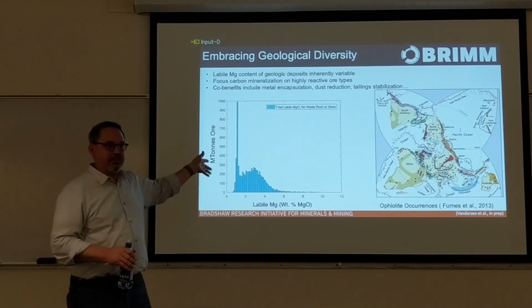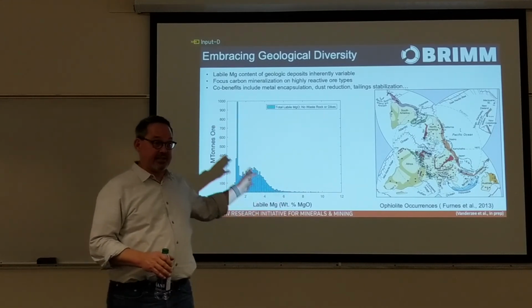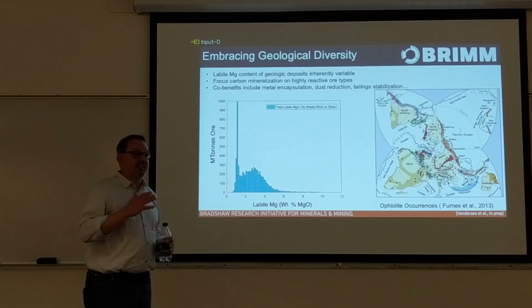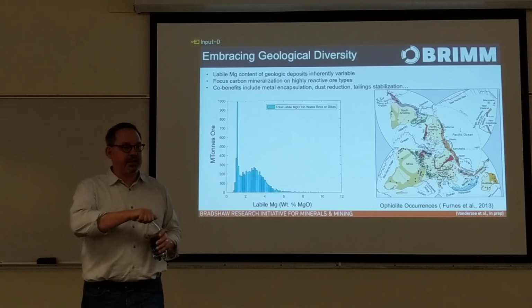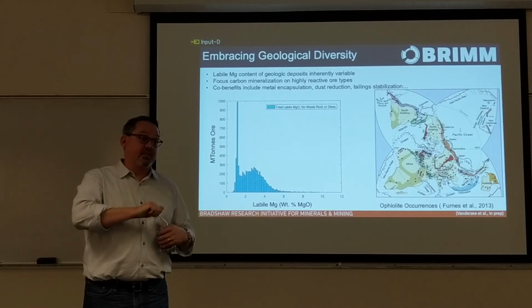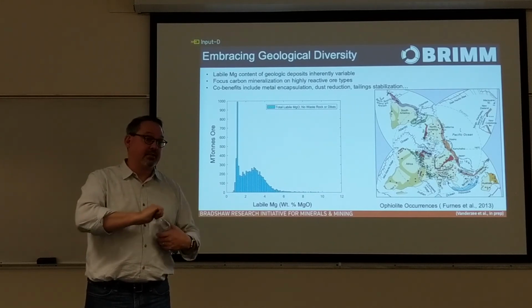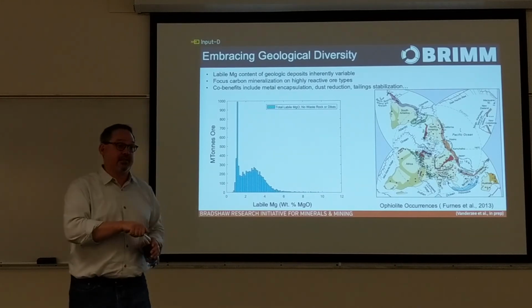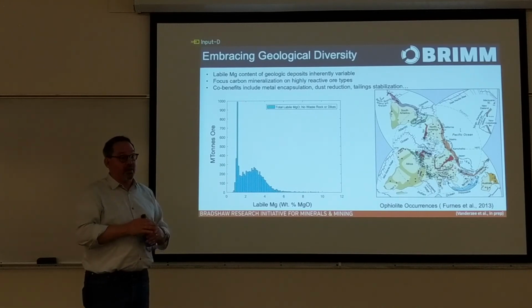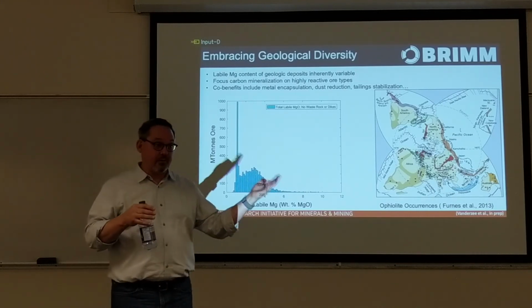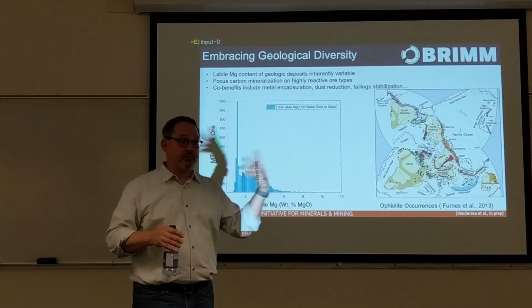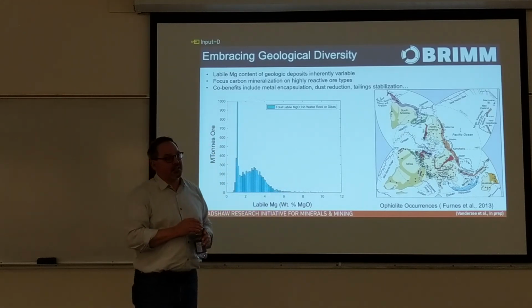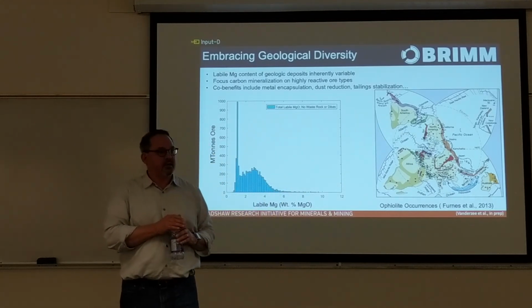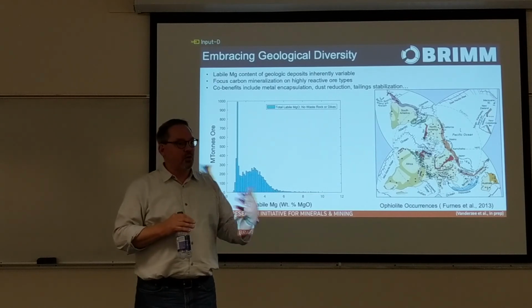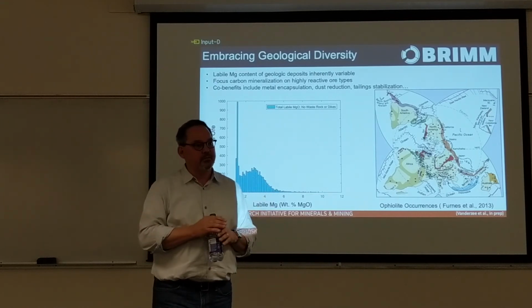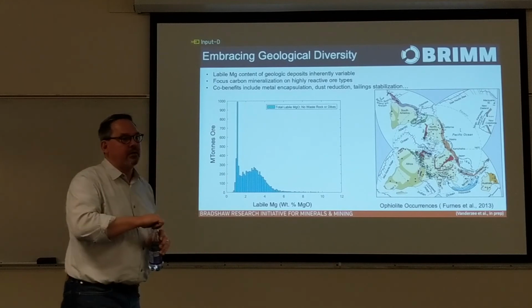The fact that we get labile magnesium measurements in serpentine, you can see those transients, suggests that same parallel dissolution mechanism operates in serpentine as well as in brucite, but that's not something that's established in the scientific literature. Not surprising, because serpentine has brucite layers, so the outer surface is brucite, maybe it behaves like brucite. Not clear that those would operate in micas. I'm not aware of any studies that have shown that faster dissolution mechanism operates.